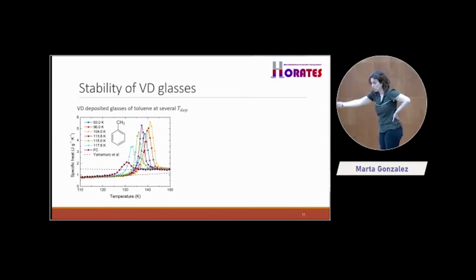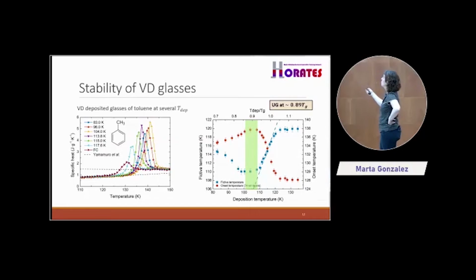It needs more temperature, it takes more time, let's say, to transform. And the area of the peak is also bigger, and that's related to the thermodynamic stability, to how low we were there before going to the equilibrium. In fact, just to summarize, here you see the curve for the onset temperature.